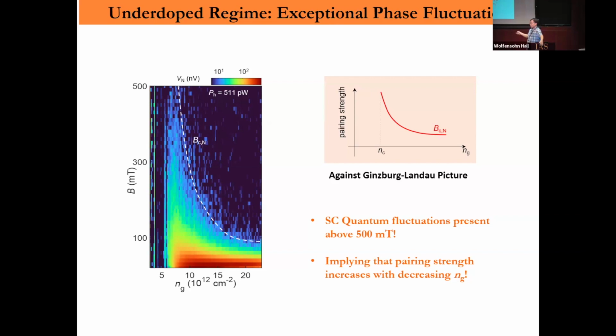So this is really the upper critical field. The resistance is not really a good probe to upper critical field, but the Nernst effect is. So that's what you see. You see the upper critical fields where electrons become normal increase rapidly with decreasing density.